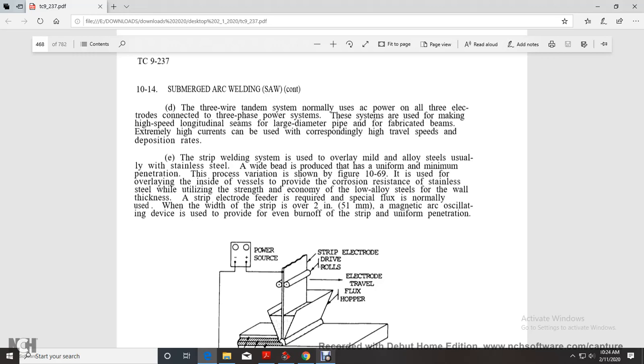Strip welding is usually used to overlay mild and alloy steels, usually stainless steel, with a wide bead producing uniform minimum penetration. This variation, shown in Figure 10-69, is usually used for overlaying the inside of a vessel, providing corrosion-resistant stainless steel while utilizing the strength and economy of low alloy steel for the wall thickness, with a strip electrode feeder requiring a special flux.